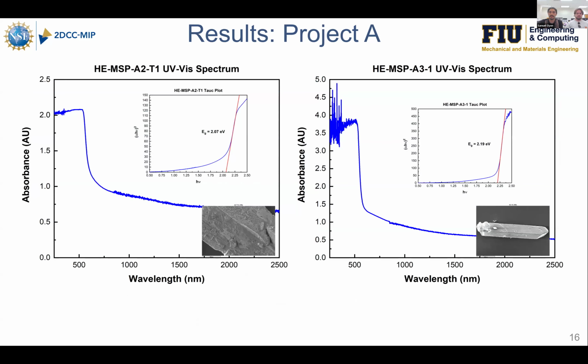but we'll move on to a little bit of UV-vis spectra that was provided by our mentor Yasu, and we can see with crystal A2 and A3 that there's some clear absorbance as we enter the visible spectrum, and the crystals actually formed relatively nicely. Granted, there's always going to be some antimony or some other secondary or tertiary phase material that can be present, even alumina from the breaking of the crucible on the crystals that can influence compositional analysis.